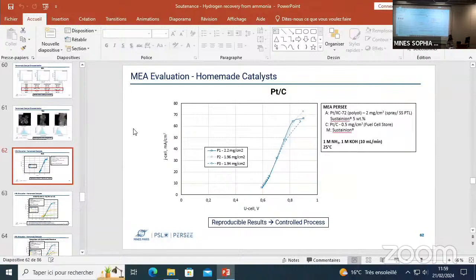I agree. Or amps per centimeter square, but of the real active surface area of the material. So it's true that what you get from your setup is amps per geometric centimeter square, which can then be divided by the loading in milligram per centimeter square, which gives amps per milligram, or divided by the roughness factor to really have the amps per centimeter square of active surface area. So here it was just a bit not really common to see that kind of unit.